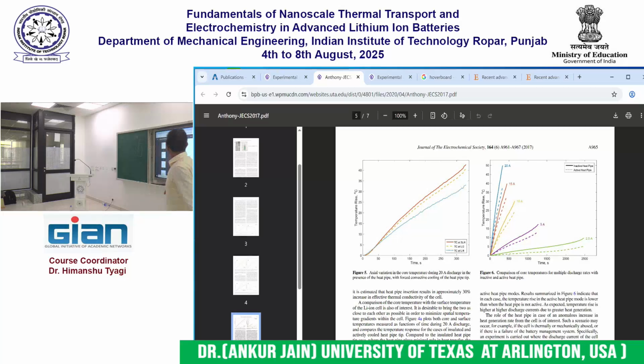So at a very low current, there is a significant reduction in temperature, and that reduction becomes more and more significant as the current goes up. So for example, at 20 amps current, which is a lot of current, the peak temperature rise was 50 degrees C without the heat pipe, and only about 37 degrees C with the heat pipe. That's a 13 degrees C temperature improvement, which is very nice.